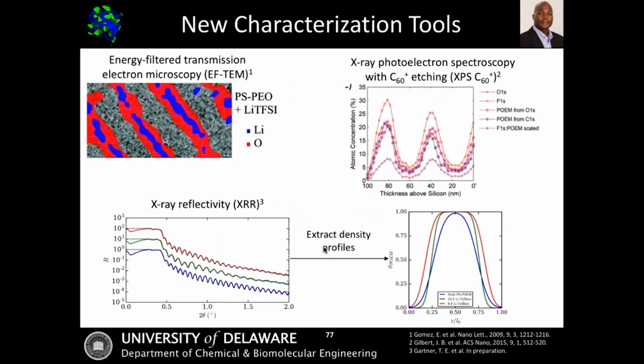So the last thing that I'd like to mention is that I can also do new characterization tools. One of the things that I can do is match some of that theory with new experiments. So here's just a couple key examples where I can do things like get density profiles from energy filtered TEM as shown in the upper left. I can also use things like XPS C60 to get density profiles again and basically locate where my ions are in my nanostructured domains.